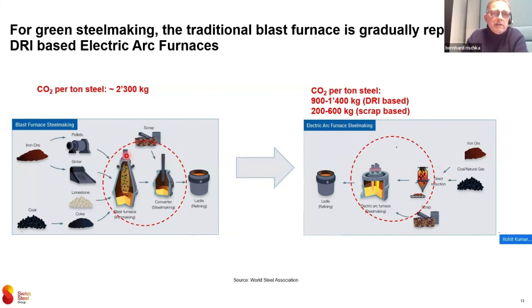And all this coke in the end is collected here on top, either as CO2 or as CO, carbon monoxide. And then it's later burned into CO2. And that's why this kind of steel making has such a high CO2 footprint of 2,300 kilograms per ton of steel. Of course, we also burn down the 4.3% of carbon coming from the hot metal in the converter, which adds another 43 kilos of C, which with a multiplication factor of 3 will be the 120, 130 kilos of CO2. But the major part in these 2.3 tons is coming from the blast furnace.